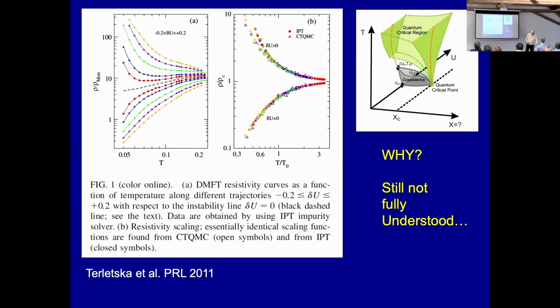So to this day, in my opinion, the fact that out of this theory you get quantum critical scaling at high temperature is not completely understood. These papers argued that apart from the plane of the physical parameters of the model, which has this phase diagram, there could be an additional deformation of the model in which you can drive TC to 0 that would control the high temperature regime, but eventually for this deformed model correspond to a quantum critical point. But this is just a speculation. Nobody has really been able to actually show this microscopically. So this is kind of open.